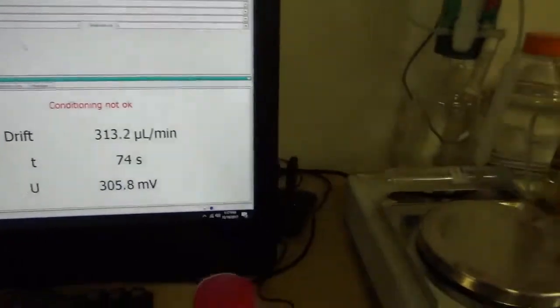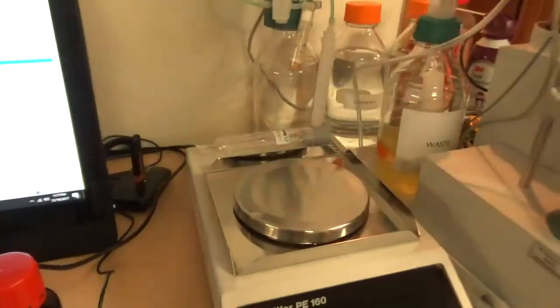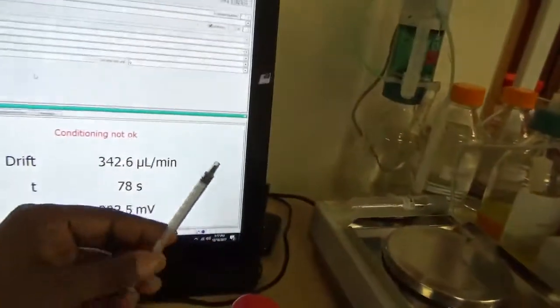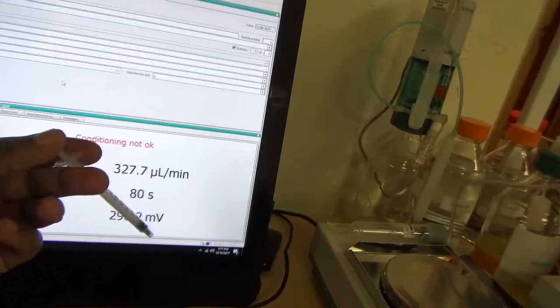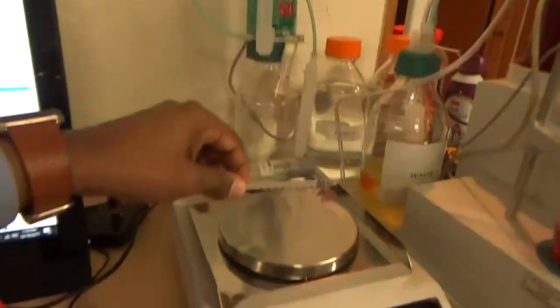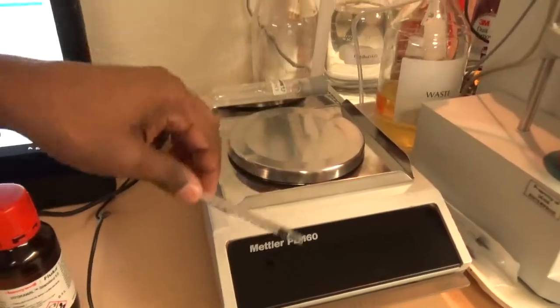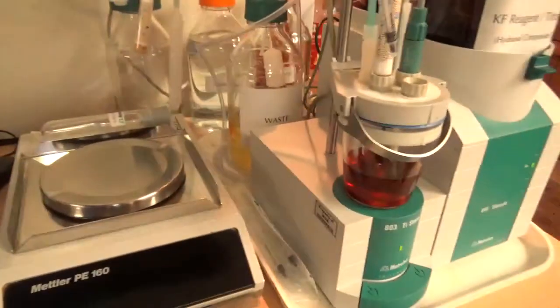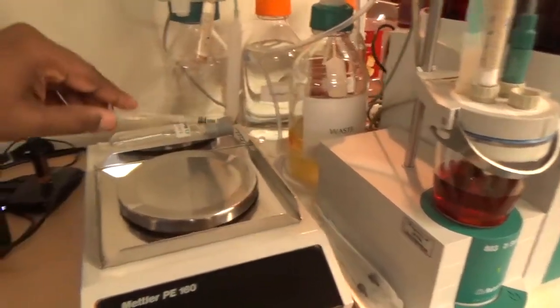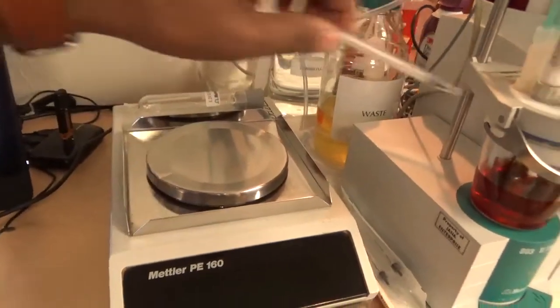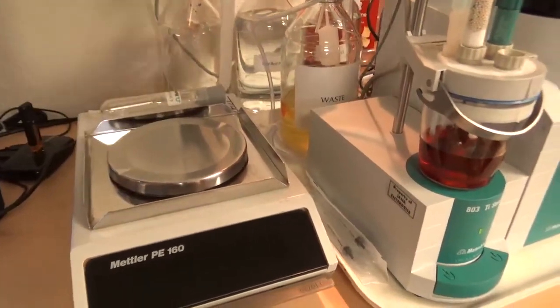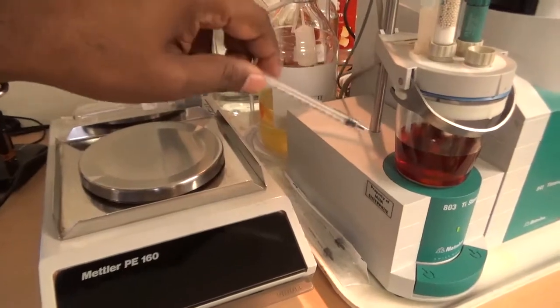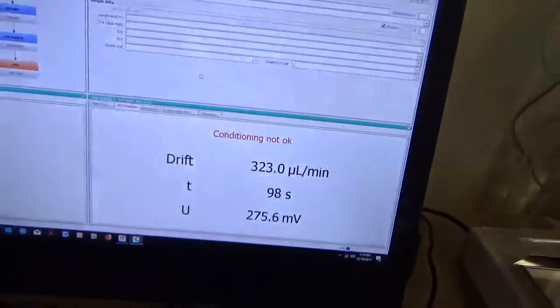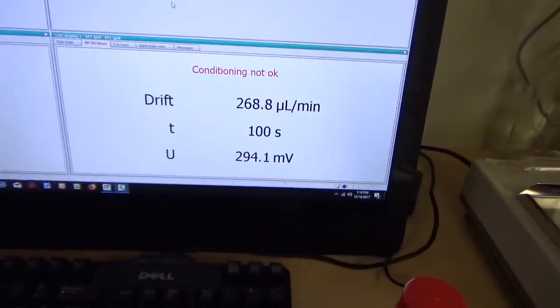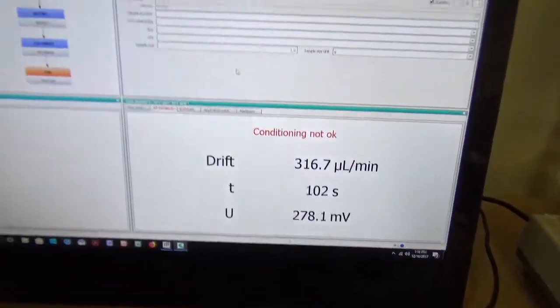So what we do, either liquid, when we add liquid we use this syringe to collect the liquid, then we put it in the balance, we tare it to zero, and then we add, after we add the sample, we take the weight again. The difference in weight is the amount of sample that is added. We add that amount of sample and the Karl Fischer titration gives the moisture content in that sample.